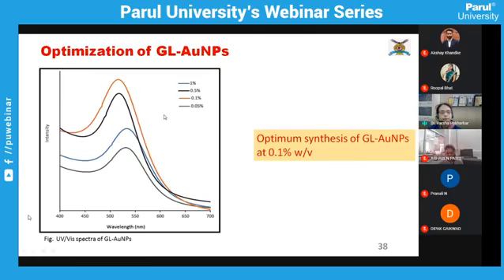For the surface plasmon spectroscopy or UV visible spectra of the glycyrrhizin gold nanoparticles, we used different strengths of glycyrrhizin, from 1% weight by volume to 0.05% weight by volume, and it was seen that at 0.1% the maximum intensity of the surface plasmon band was obtained around 520 nanometers. Therefore, 0.1% was considered the optimum strength of glycyrrhizin that we can use.